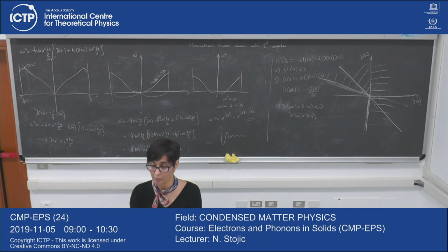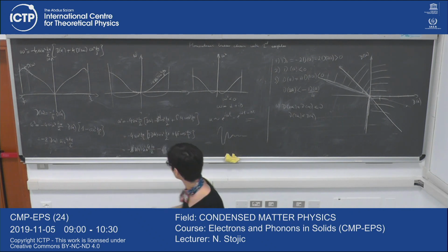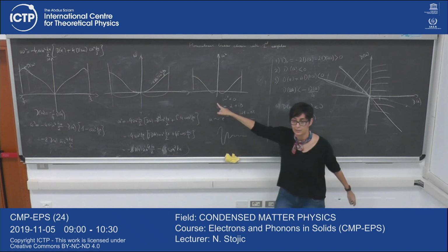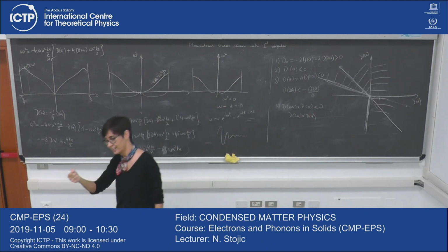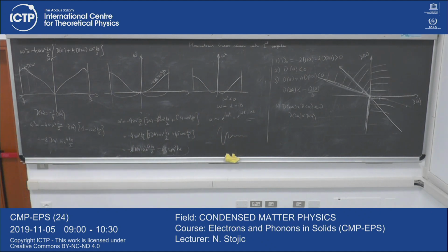This dipole moment lowers the energy so much that the restoring force is not strong enough to bring the atom back. So this kind of process, where you go in the slightly negative path, can freeze a ferroelectric structure.